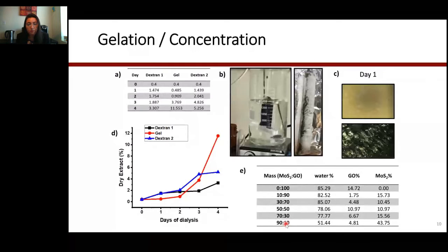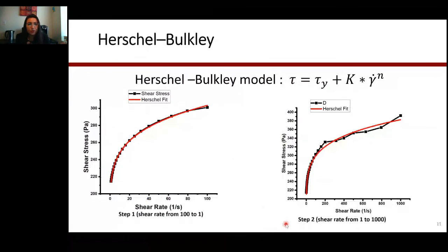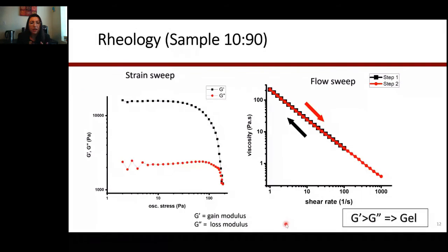This was great. Even though the MoS2 was bulk, we still were able to mix it well and obtain the gels. Having obtained these different concentrations of gel, we have to understand a little bit of the rheology. Leanne just went over a lot about that, so I won't go into much detail because she did a great job. What I want you to get from here is how the material behaves and how we proved that this was actually a gel. There were 2 points. In our materials, our storage modulus was always above the loss modulus, which means that for all our materials, we actually obtained a gel. And what was really interesting too was that it was viscoelastic.